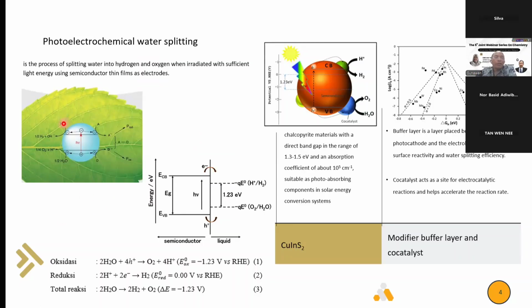Here is the process of reduction of water, producing hydrogen, and here is the production of oxygen from the process of water with holes. From the energy here, there is a difference in energy between O2 and H plus. The difference is 1.23 electron volts. So to split water, theoretically we can use a potential of around 1.23 volts. But in practice, it is more than that value.